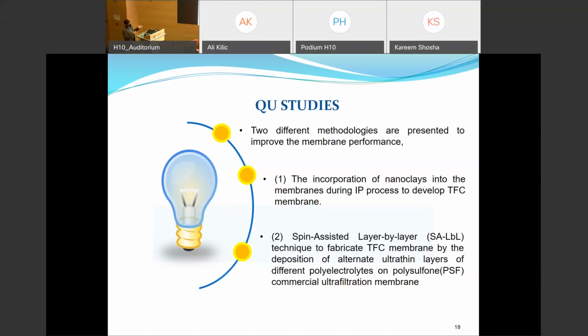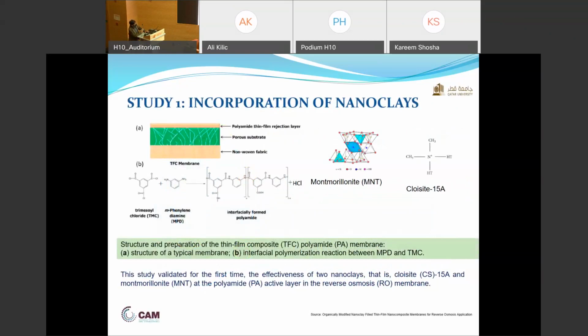The currently used TFC membranes are made by interfacial polymerization. There is some complex manufacturing process, so we try to make a simpler process. So these are two studies we undertook. We have used two nanomaterials, one called montmorillonite and the other one called cloisite. They are incorporated in the thin top layer of the polyamide in very low percentage, less than 1%, 0.2, 0.5%. And for the first time we have validated the effectiveness of these nanoclays.